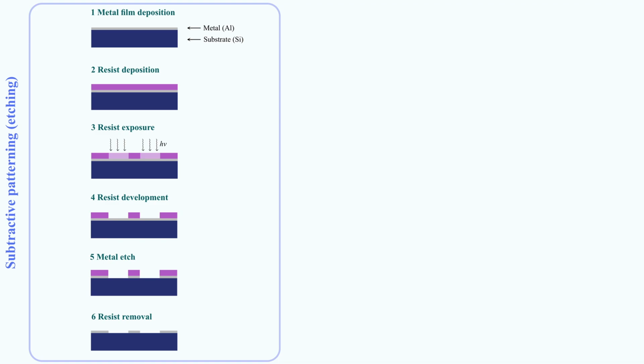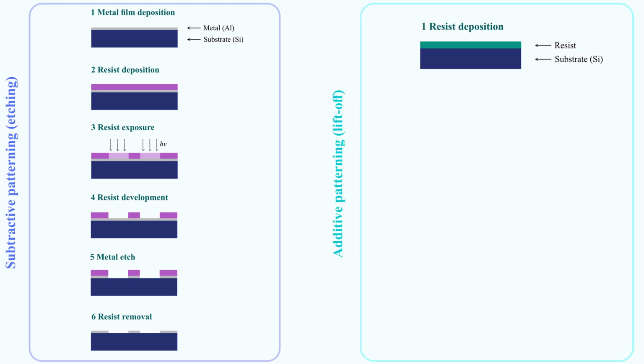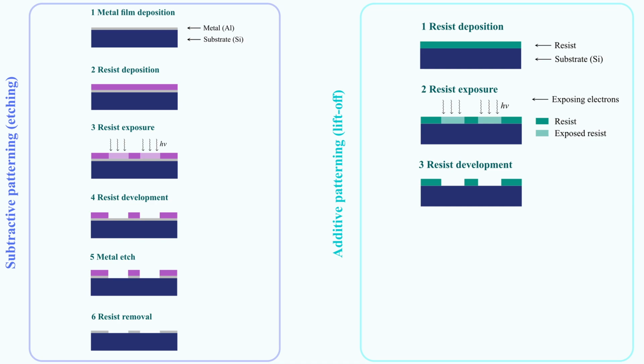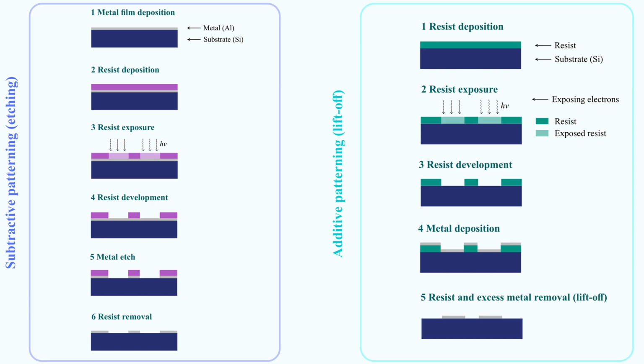What we're going to do now is first deposit a resist on top of the substrate where we want the junctions. We're going to pattern this resist and only then deposit a metal. Now we have some metal in direct contact with the substrate and some that is spaced by the resist. If we then dissolve the resist, then whatever metal was on top of it will be removed and only the metal in direct contact with the substrate will stay.